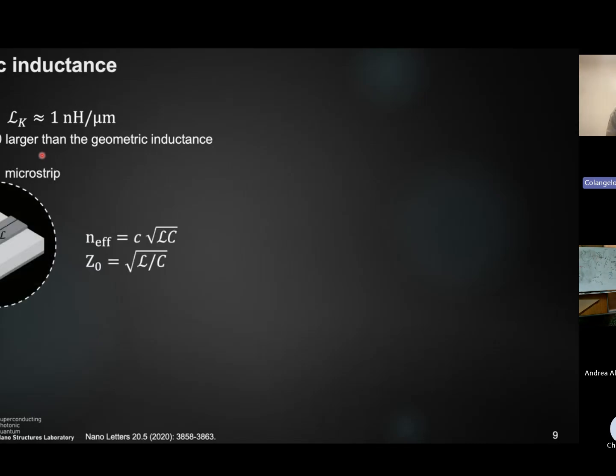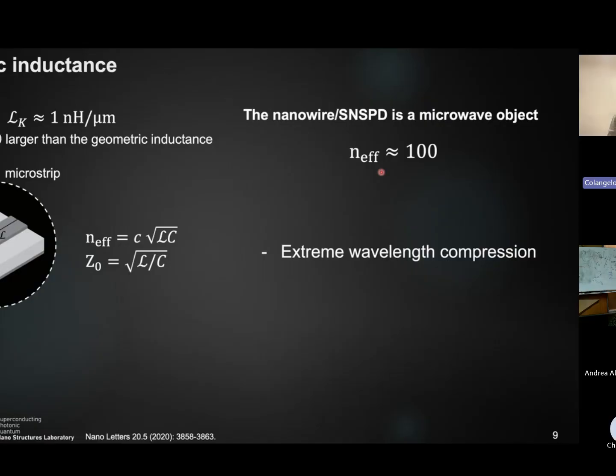So what happens really is that when we treat a nanowire, we are actually dealing with a microwave architecture. We're dealing with a microstrip when we have our nanowire referenced to a ground, which is the back reflector of the optical cavity. So now if we plug in these numbers here, this 1 nanohenry per micron, and also calculate the capacitance between the nanowire and the ground plane, we do realize that the effective index is actually about 100.